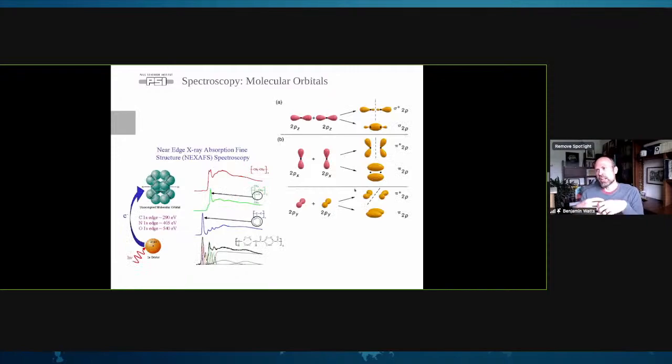So in terms of the unoccupied electronic states that these electrons can be put into, for organic materials, these are typically the antibonding states. So when we have two atoms come together, the states will split, and they will form a lower energy bonding orbital that the electrons will go into to form a covalent bond, and an antibonding orbital, which will remain empty.